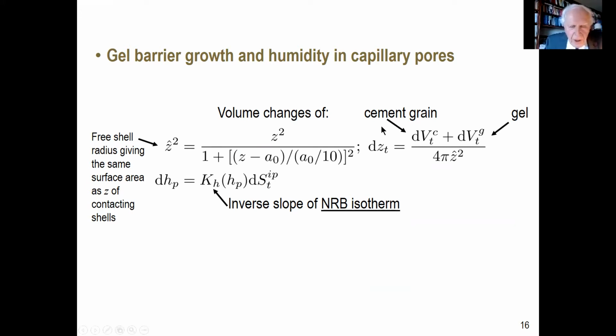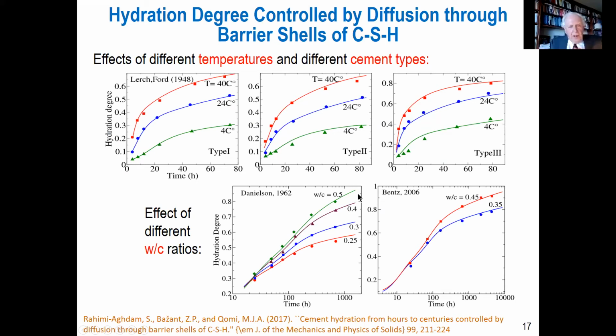So there must be a correction, which can be obtained asymptotically, matching between fully hydrated material, fully filled by hydration product, and this there is free. All right, and then I would like to show that it works. So hydration degree is shown here on the ordinate versus time. This is in linear scale, this is in logarithmic scale for various temperatures, for various types of cement, and for various water cement ratios.